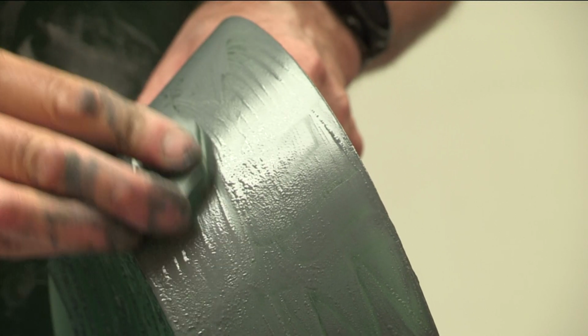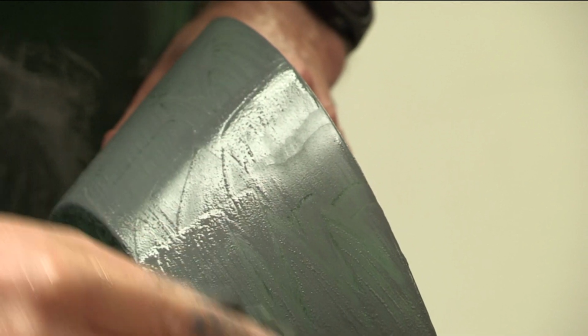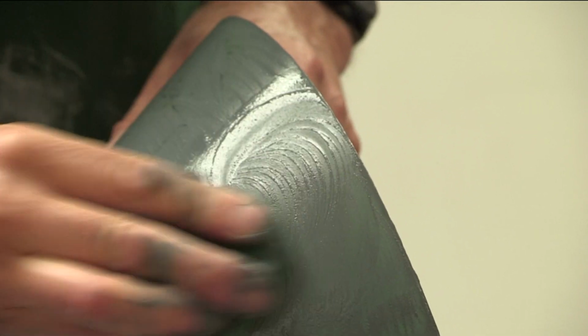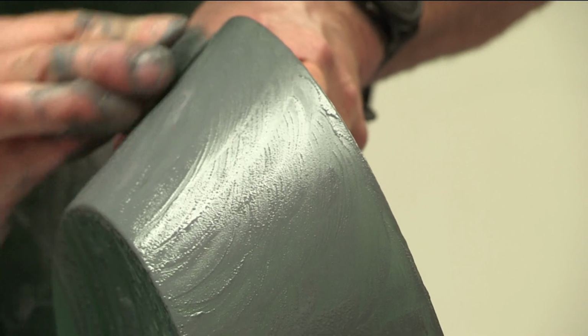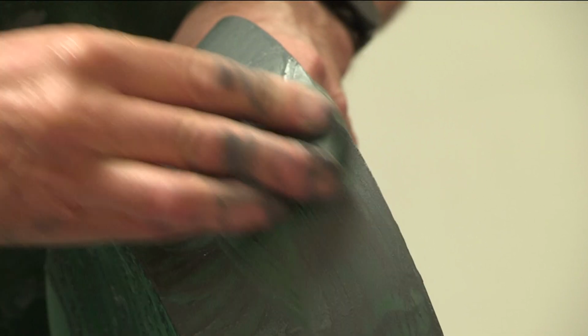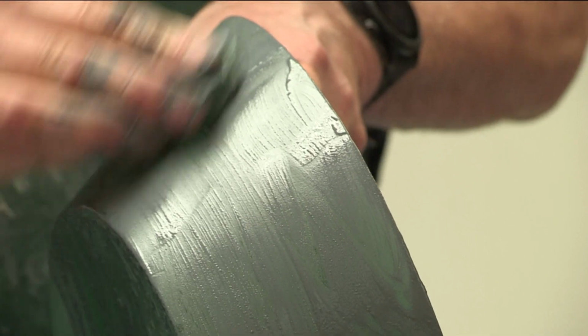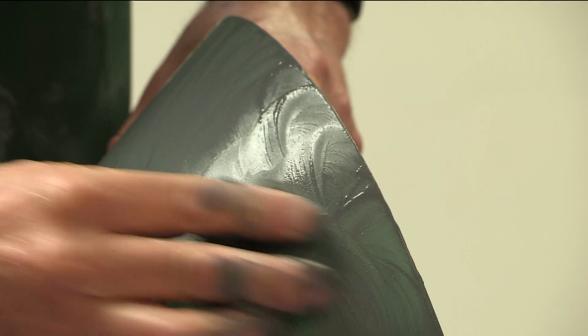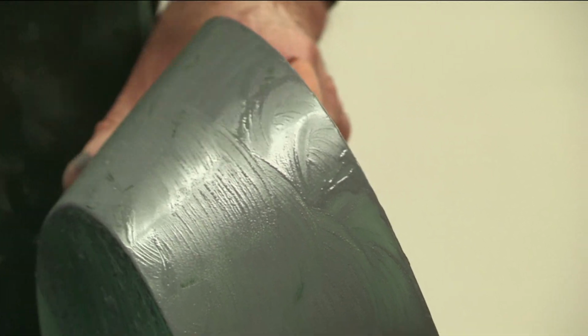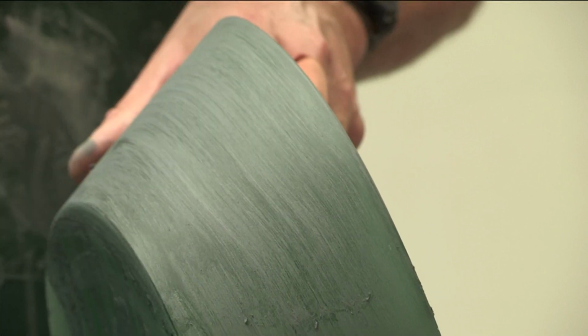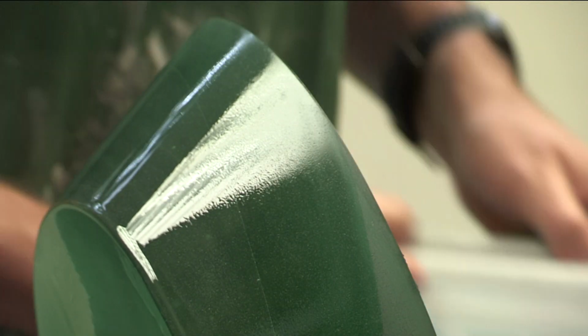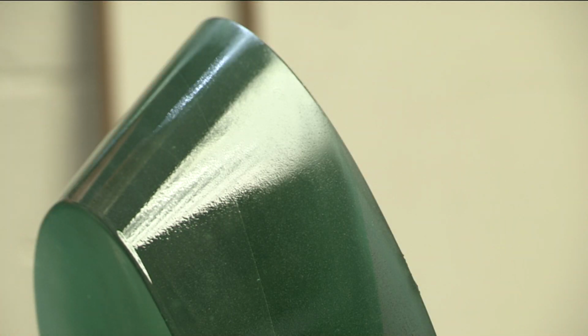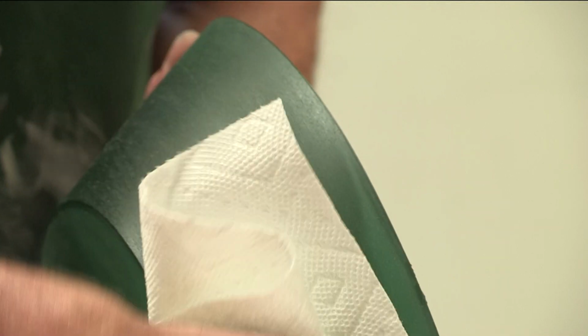Quite often these are quite flat shapes or even curves, and grinding glass on glass is a really easy way to affect the surface. If I was trying to make more of an acute angle, like on the surface of the piece that I showed you at the beginning of class, that would require a slightly different piece of glass or a different shape to help me get that form. So for that I use diamond pads and other tools that I purpose make. We customize to fit those surfaces.